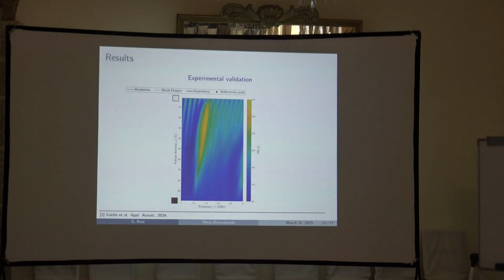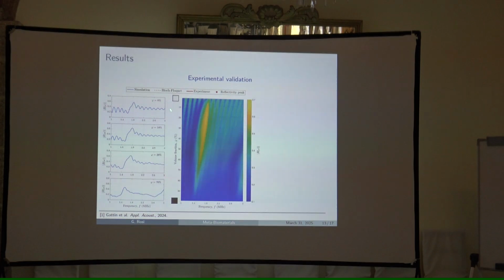If we put a chart, let's say, of the volume fraction here and the frequency response here for different volume fractions, you have this zone of high reflectivity, which basically corresponds to the presence of the bandgap. All the graphs I will present will be slices of this graph, which means that we perform the experiment on one configuration, and we have the frequency response. And the simulations for different volume fractions, you can do 70, 29, 18, and 8. These are the positions of the band gap as forecast by Bloch frequency analysis.